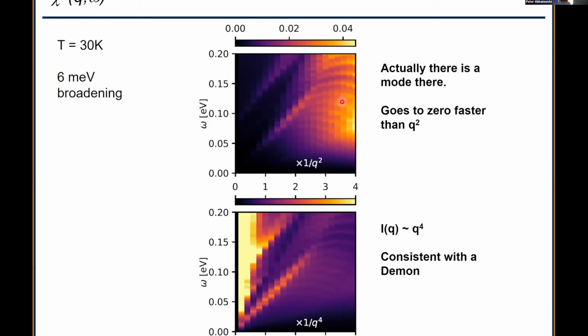But it clearly completely fails for this high energy mode, by the way. So if you look at the strange metal physics, it utterly, dismally fails to predict the experiment at that kind of energy scale. But in the low energy regime, it seems to work.